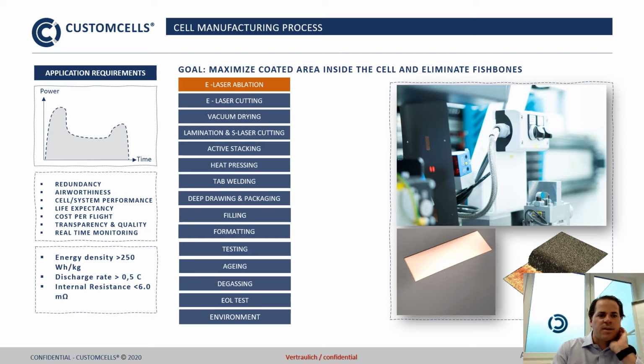Itzehoe is, as I mentioned before, a series cell manufacturing facility, and we run some processes quite different from a typical or standard cell production to enhance the quality of the cell. It begins with laser ablation, and after that we have laser cutting of the electrode, vacuum drying, lamination and separator laser cutting, active stacking, heat pressing, tab welding, deep drawing and packaging, the filling process, formatting, testing, aging, degassing, and the end-of-line test, and of course we can also influence the environment in the production. So beginning with